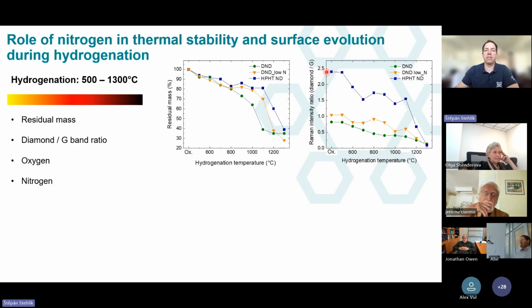So here we see in the beginning a nice prominence of the diamond, but then some sp2 carbon is formed as a result of this thermal hydrogenation. It's also quite well known, but when we exceed 1100, we get a severe graphitization. So you can see that the standard DNDs are a bit less resistant to the temperature than this low nitrogen DND, which behaves more like these HPHT nanodiamonds.